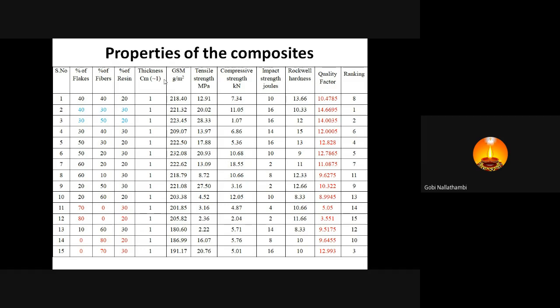But here we only depend on the resin. The resin curing temperature is 180, so we heat the sample at 180. Even so, there may be some interaction between the fiber, the resin, and also the flakes. Because of that, even though the resin proportion varies, when the proportion of flakes and fiber varies, there is a variation in the properties. So we can conclude that the impact of resin and also flakes and also fiber decides the quality of the composite.